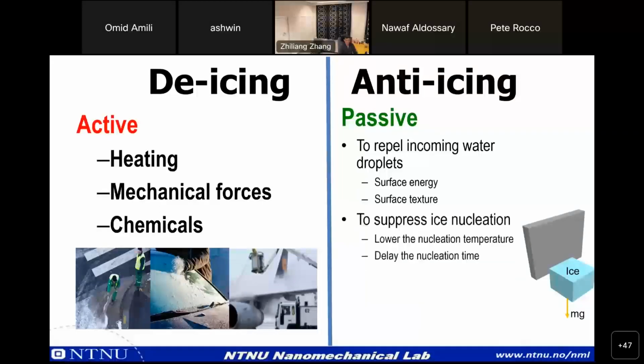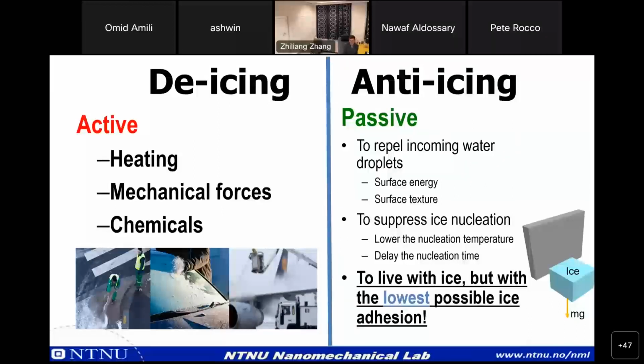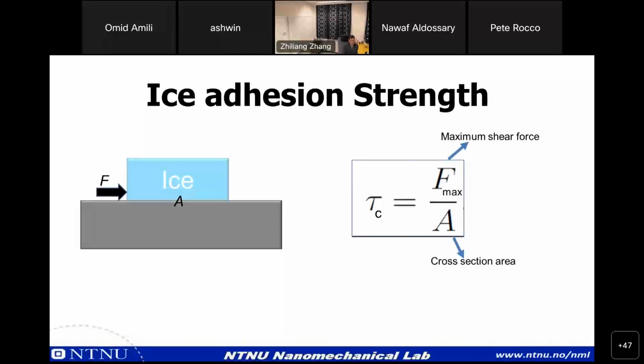Okay, so this is the first strategy. The second one, of course, is to suppress the ice nucleation. So even if we have water, we can suppress the ice nucleation. So either we can lower the nucleation temperature or delay the nucleation time. There is a lot of research in these two aspects. Unfortunately, no matter how hard you try, when the time is long enough, when the temperature is low enough, ice will come in the end. So the strategy we have chosen is to live with ice, but with the lowest possible ice adhesion. It's called ice adhesion strength, in fact.